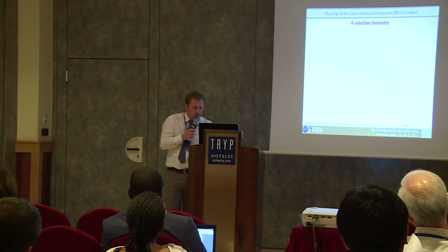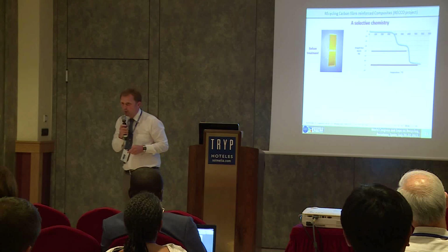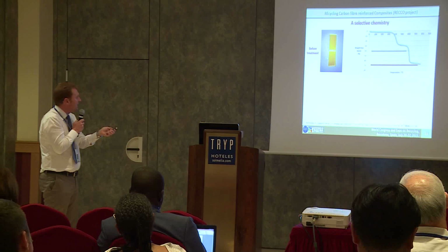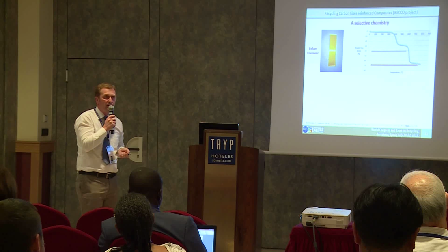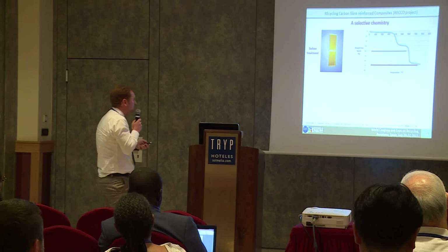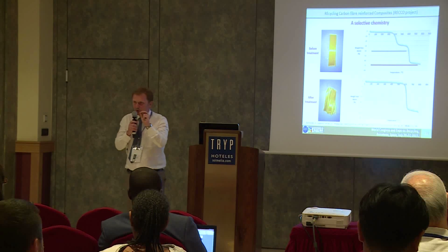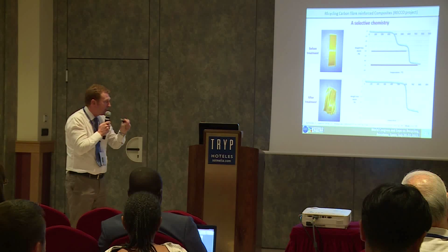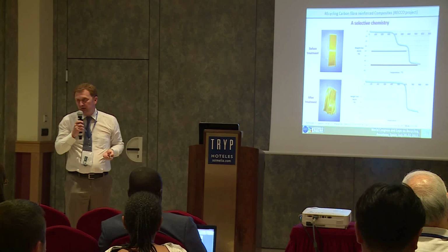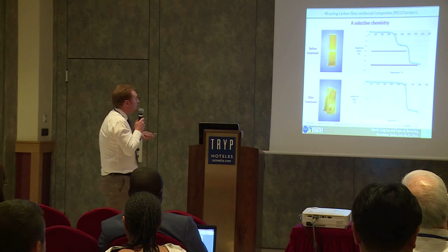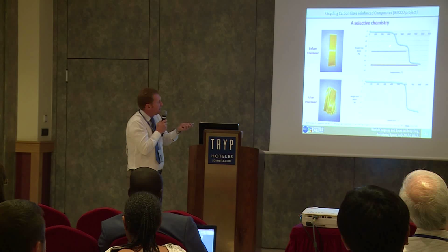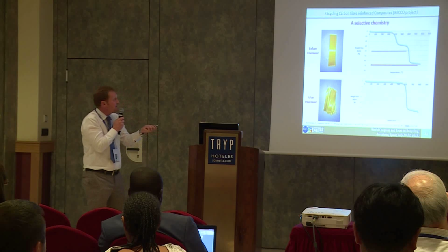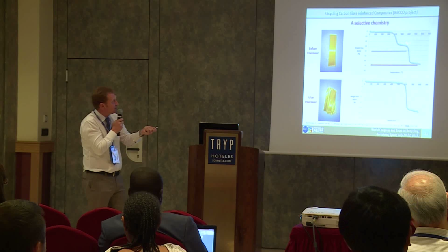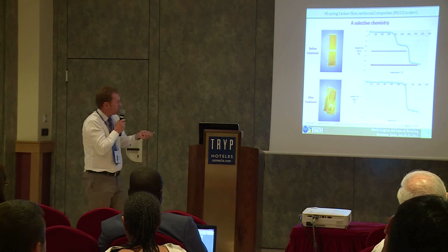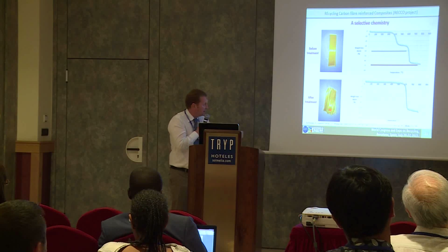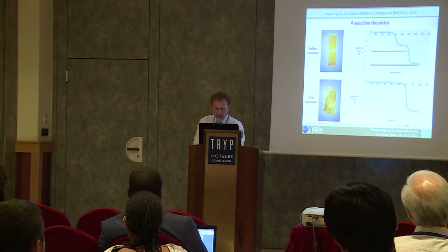A very interesting result for the chemist: we proved that it was possible to be selective in the chemistry, and you see here a composite made with a Kevlar fiber, polyaramid fiber, in an epoxy resin. And it's possible to control the chemistry in order to just hydrolyze the epoxy resin and keep the polyaramid fiber. So as chemists, we were very happy with this result. And you have here the proof with thermogravimetric analysis. You see here in the composite the resin and the fibers, and after the treatment, you have just the fibers. And we have now an end user for this kind of material.